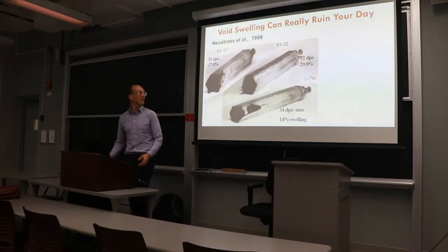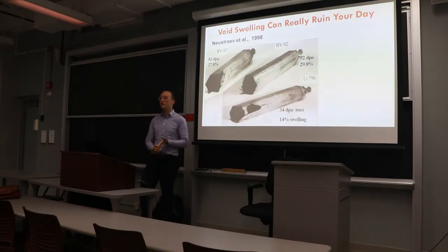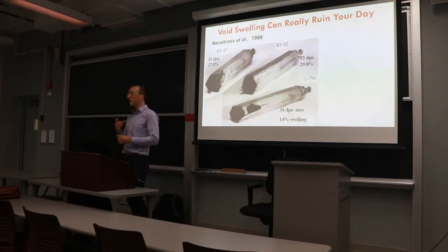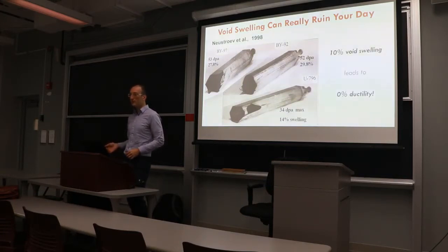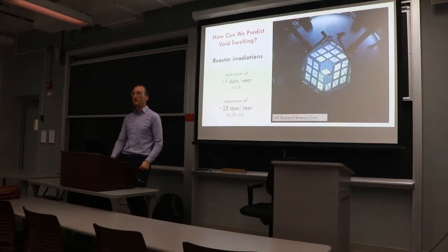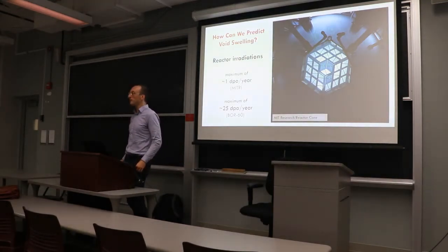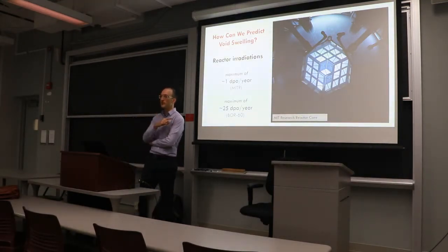Like in this picture of fuel channel boxes from a Russian sodium-cooled reactor that failed because of void swelling and reduced cross-sectional area. Because once you get to about 10% void swelling, you get 0% ductility. Everything's brittle and everything falls apart. So we can do these tests in the MIT reactor, where we can get about 1 dpa per year, but if we want to know whether this reactor is going to last for 50 years, we have to irradiate for 50 years.